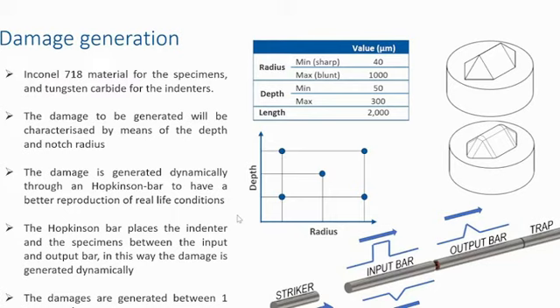You can see on the right an example of the indenter that we are using for the dynamic indentations. So considering this range of damages, we built a test matrix that considers 5 different damage configurations that takes into account 3 different depths and 3 different radii.